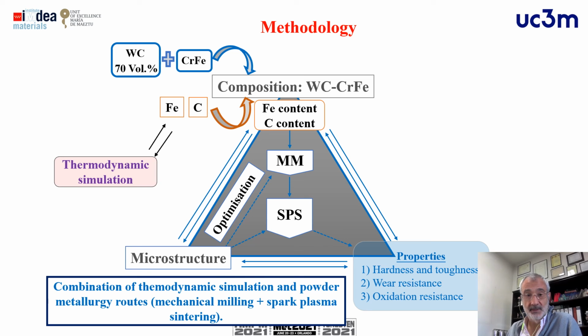So the methodology is to design the composition using this chromium iron binder, but through thermodynamical simulation we have decided to introduce iron, because iron can improve the densification of these cemented carbides, and also carbon in some specific amounts in order to reduce the formation of some negative phases that can be produced during the sintering process. So this combination of iron and carbon will be predicted by thermodynamical calculations, mathematical simulations, and then we will develop the bulk materials by spark plasma sintering, and we will analyze the microstructure and the properties. In this case, we will see the hardness, the fracture toughness, and we have some results also regarding the wear resistance and the oxidation resistance of these new hard metals.